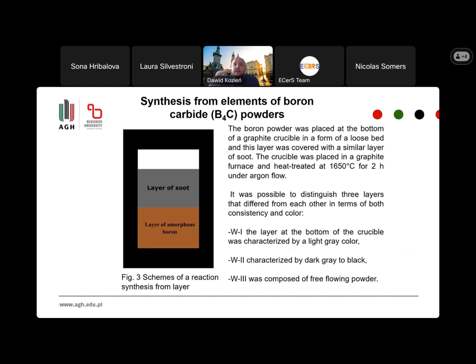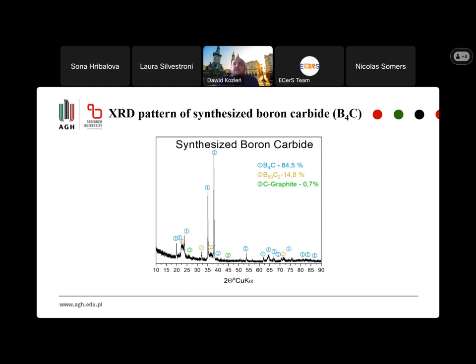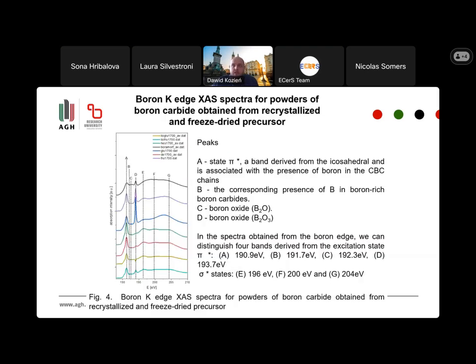This is specific to how we prepare it: we have a layer of amorphous boron and on it a layer of soot. And we can separate a very pure powder. You can see that after sintering, we have a powder that has less than 1% graphite in its composition. And after that, we checked this at the Solaris synchrotron beamline.